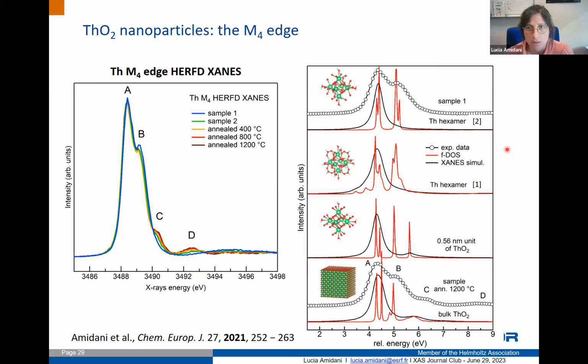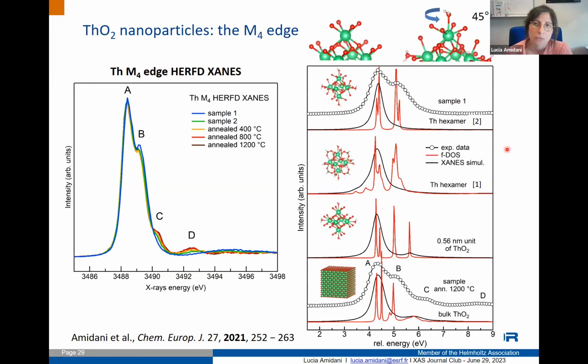And why is that? This is mainly because if I take the chunk of bulk that I cut, I still have the octahedral symmetry locally. But in real clusters, the oxygen at the surface are rotated by 45 degrees, the symmetry is lost, and this is why the peak is lost as well.